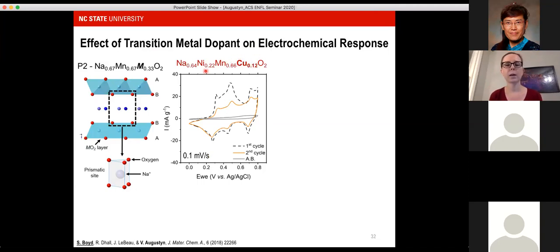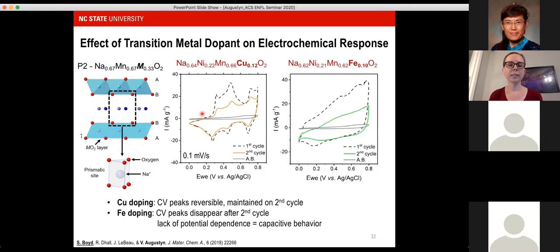So for example, we had this composition that had manganese as well as a little bit of nickel and copper. In the first and second cycle, there was a capacity decrease, but the same peaks were present for the first and the second cycle. On the other hand, if we took the same material but now replaced the copper with iron, we saw less pronounced peaks during the first sodium deinsertion process. And after that, those peaks disappeared. There was essentially almost no potential dependence of this material, which we consider to be capacitive behavior now.